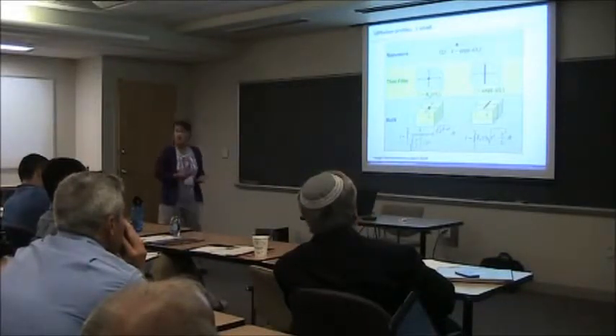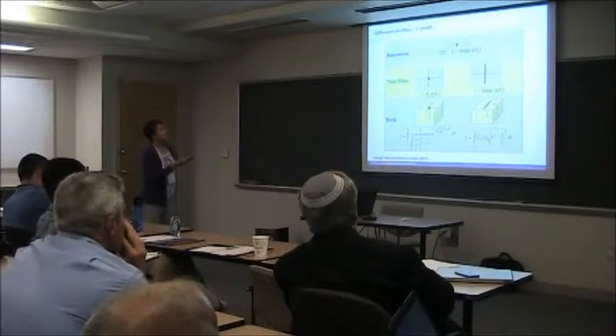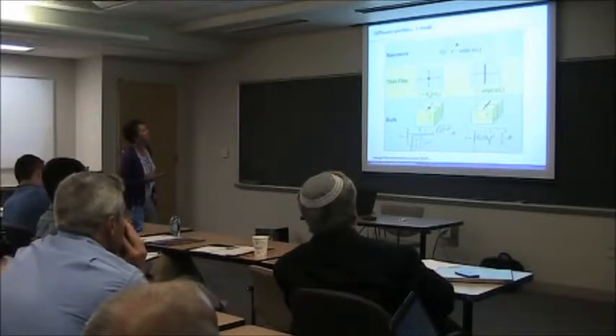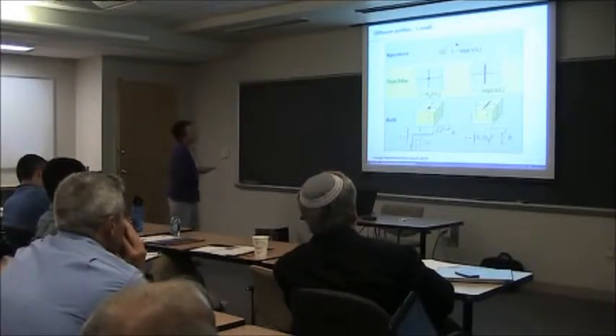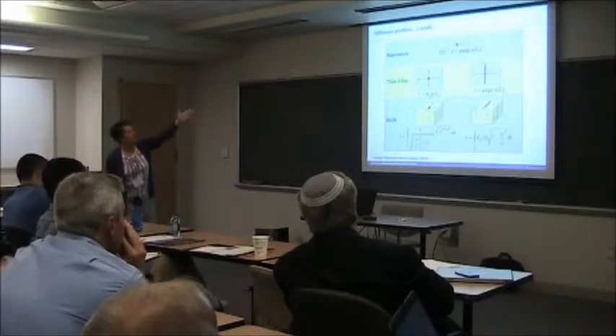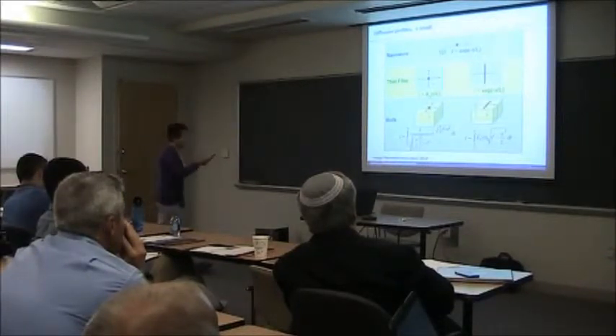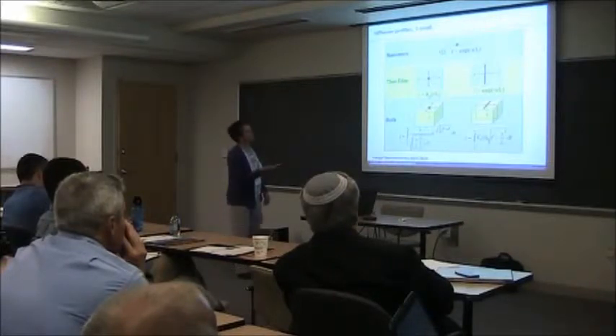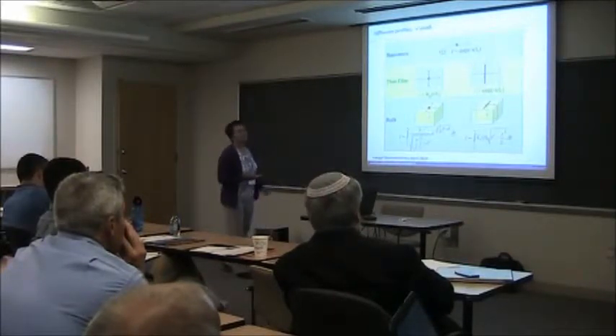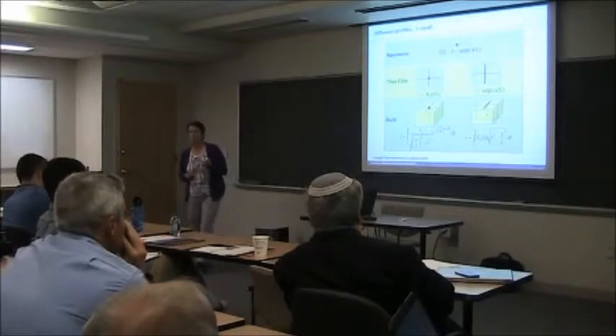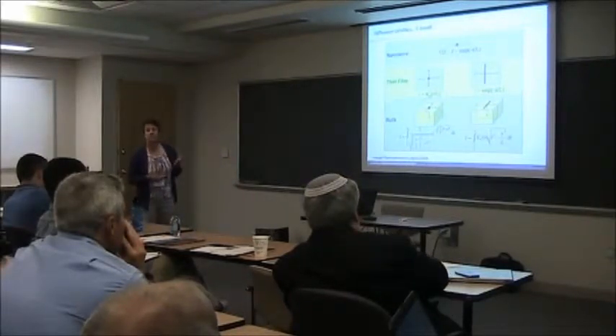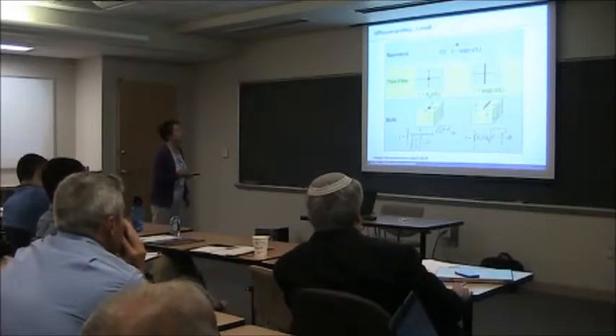Now you can do this in all kinds of geometries. You can use a point source on a nanowire, and it's quite nice, and it's an exponential decay. You can do a point source on a thin film. If you're smart after a while and your material is uniform, you realize you should be doing a line source and integrating. You can do point sources on bulk or line sources. This is in the assumption that the surface recombination is small. So we don't have to have a heterostructure, although a lot of times if you do, you can do some very nice work. But you don't have to.